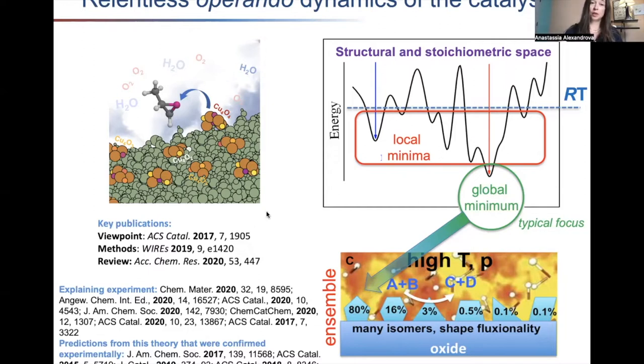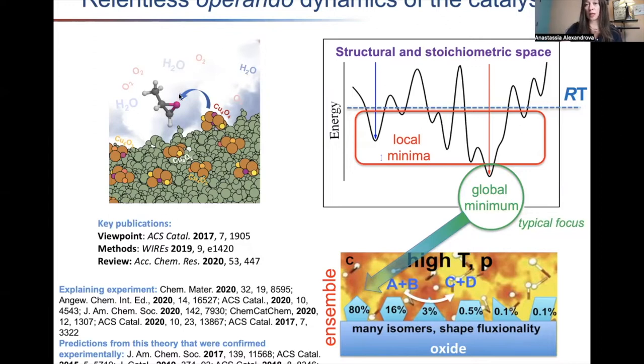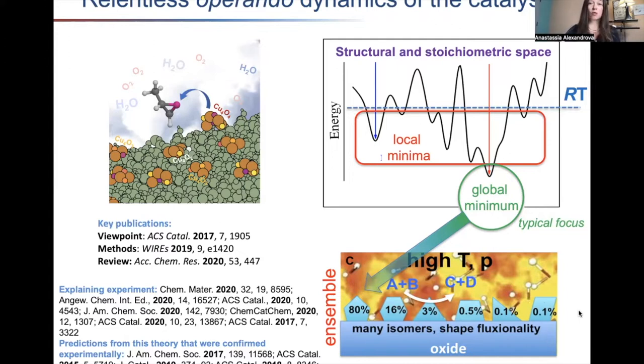In this cartoon — these are results from actual simulations — we have a fixed number of copper atoms, only three or four, in a catalyst, but varying numbers of oxygen atoms sitting on amorphous alumina supports, also differing in the site on the support they occupy. All these minima can be very close in free energy. If you draw an RT line, many minima are thermally accessible, meaning the catalyst is not just one global minimum but a soup of many states simultaneously present.